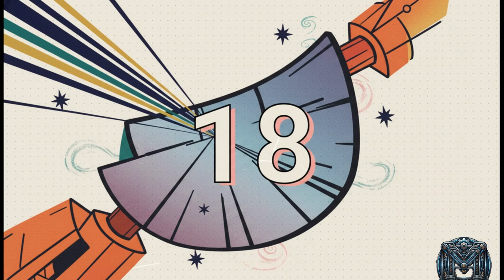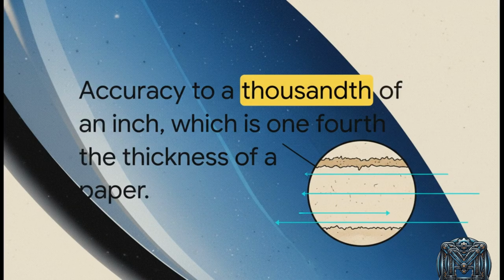For a year and a half, massive machines using diamond tools physically grind away up to 2,000 pounds of glass from the surface. And as they grind, they are constantly testing the optical shape by bouncing laser beams off the surface to catch even the tiniest microscopic flaws. When that polishing is finally wrapped up, the shape of the mirror is accurate to about 1/1000th of an inch. To put that in perspective, that's roughly 1/4 the thickness of a standard piece of paper. It's completely wild. This gives these massive 26-foot wide Earth-based mirrors a nanometer-level precision that rivals, and in some cases even beats, the legendary Hubble Space Telescope.